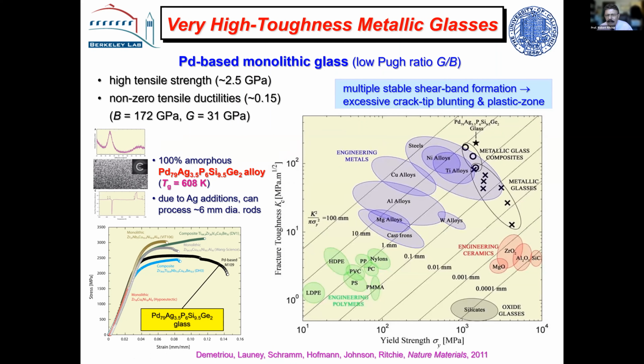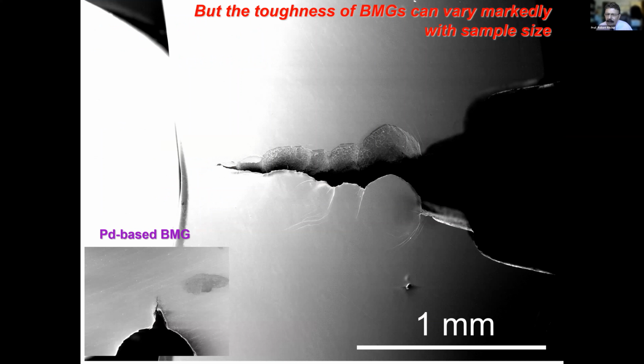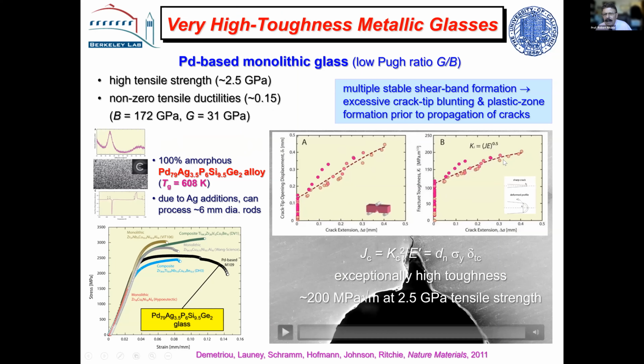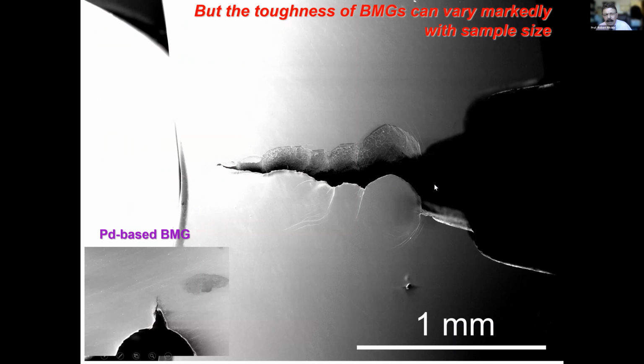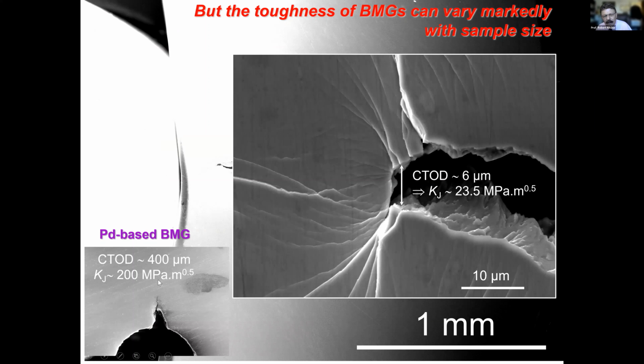And then we started to look at different size samples. So we had this toughness of 200 here in a fairly small sample. We got the material from Germany and we looked at a bigger sample. And instead of getting a toughness of 200 megapascal root meters, we got a toughness of close to 20 megapascal root meters in the same material, but a different sample size. This is a much bigger sample size than this one. So what's going on here?